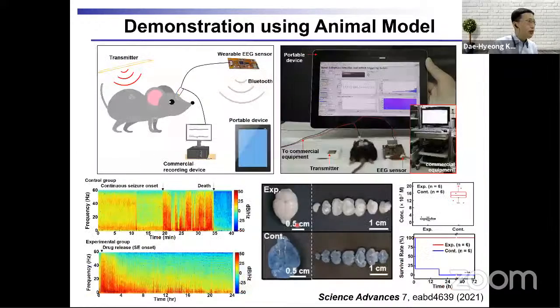And we demonstrated this system using an animal model. We induced status epilepticus in a mouse model and measured EEG using our device. And when SE was detected, the command signal was delivered to the power transmitter, and this power transmitter generated radio frequency signal to transfer power to this implanted device, and immediate drug release was made in the experimental group, while in the negative control group, this system was not applied, so the immediate drug delivery could not be made. And according to the result, all mice in the experimental group survived after 72 hours, but in the control group, all mice were dead within 24 hours due to the brain damage.